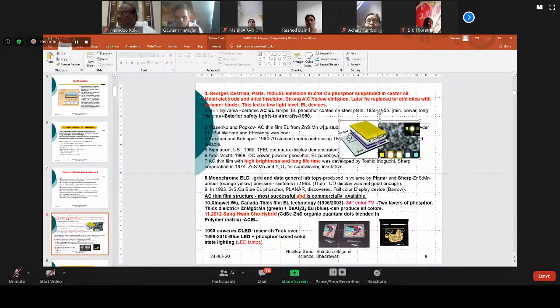Then a monochromatic electroluminescent display for the Grid and Data General laptop was produced by Planar Company and Sharp using zinc sulfide manganese, amber color. You see this display. This is the amber color, which was the EL device extensively bought in those days, 1983. In 1993, an EL device had a drawback. The blue phosphor was not good. And first time in 1993, strontium sulfide cerium was reported as a blue EL phosphor. And then full color display devices started being made. But the AC thin film structure is the most successful and commercially available even today.